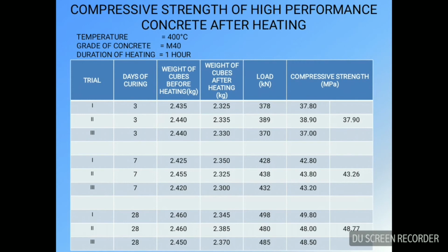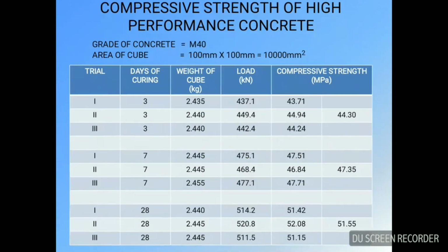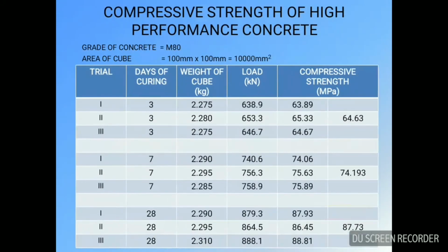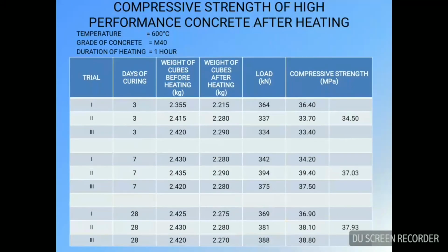As you can see here, the strength of concrete came around to be 48.77 after heating it at 400 degrees Celsius, while for M40 at normal room temperature it was around 51.55. There is a small degradation in the compressive strength. Now next comes M40, which was heated at 600 degrees Celsius for about 1 hour. Similarly, the compressive strength was noted with the same procedure.